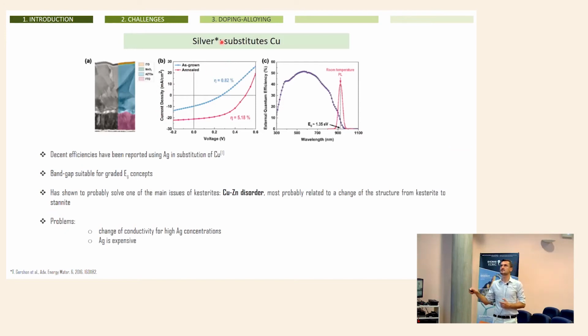Silver gives very interesting properties to copper, because when you add silver, which is much bigger than copper, the copper-zinc exchange is no longer easy from the thermodynamic point of view. And then silver tends to go to the right position and not exchange easily with the zinc. This reduces the possible copper-zinc disorder. But even with this, the efficiencies obtained up to now are not so high, and this is because there is a problem. Silver tends to change the conductivity of kesterite, converting kesterite into an N-type material. And as I told you before, we are very bad at making devices with N-type material.